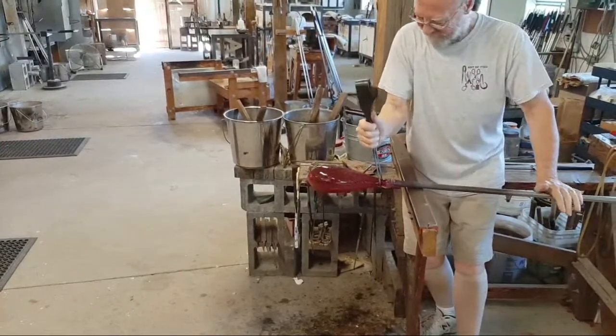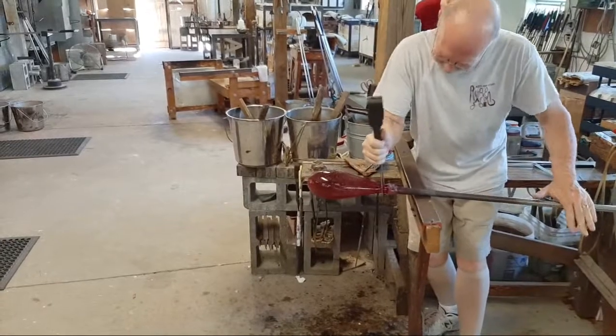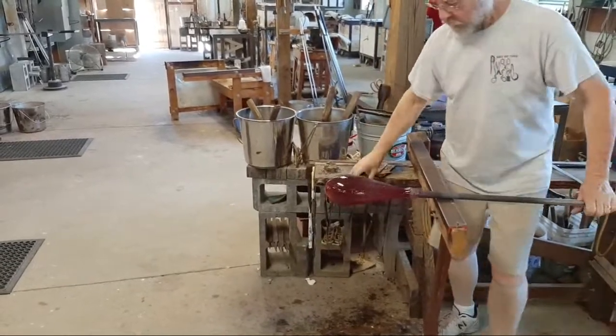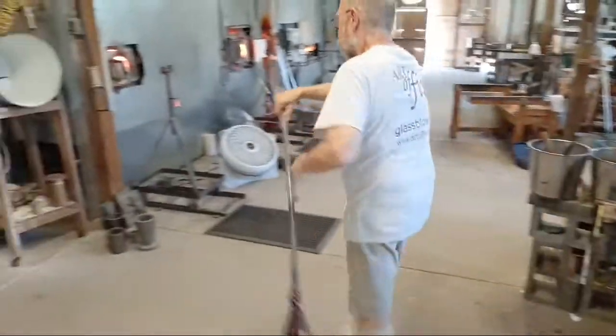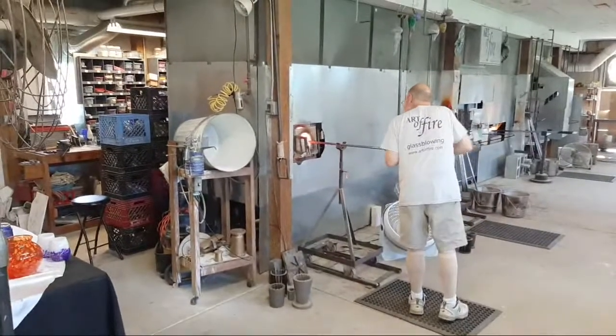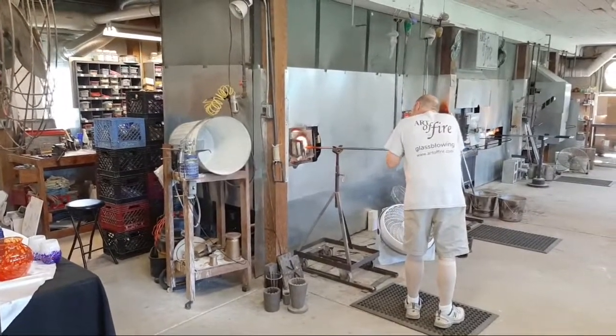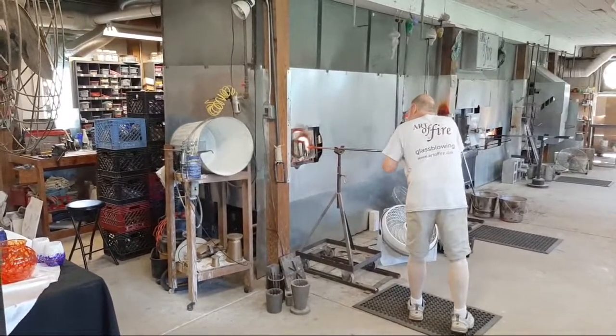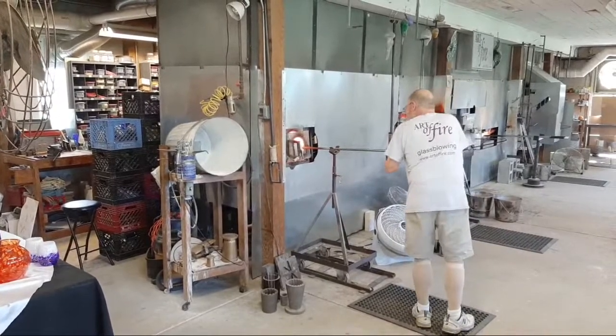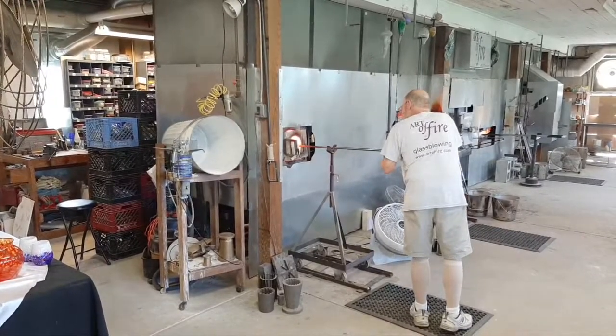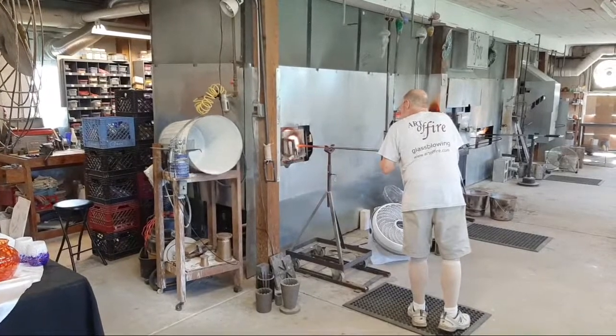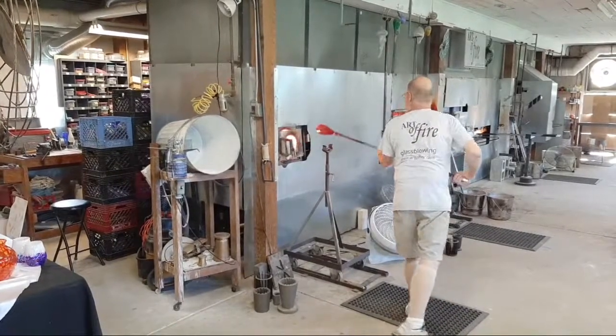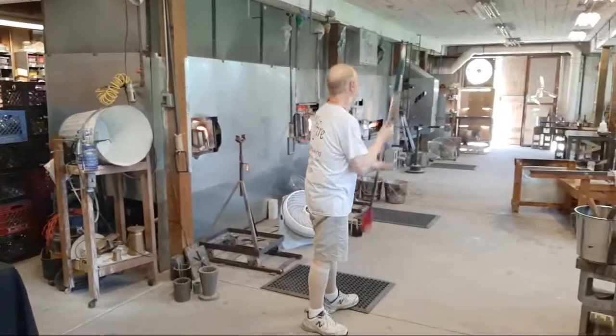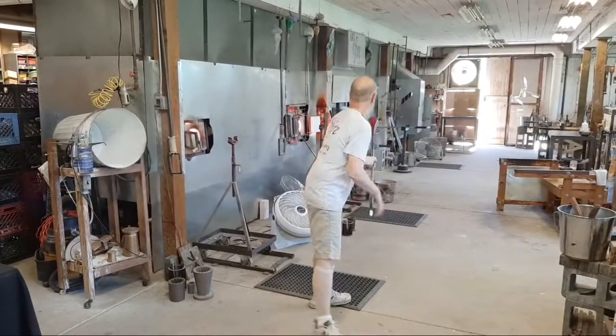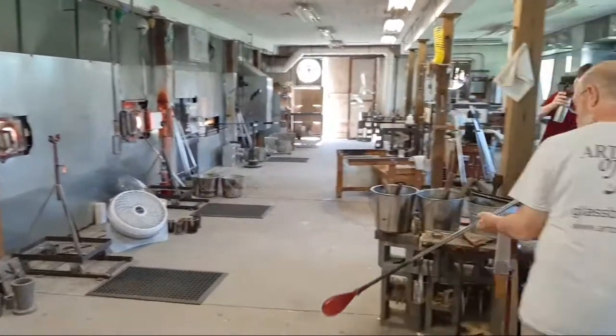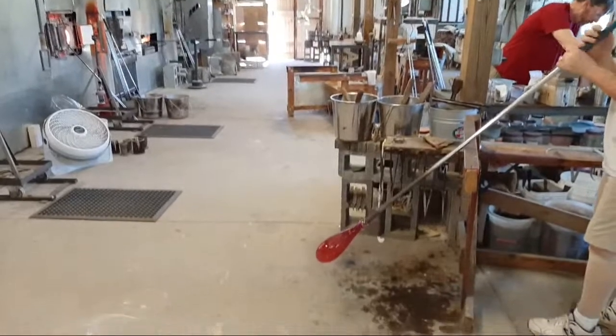When it breaks free of the blowpipe, the glass is going to come loose at its weakest point. And we want to make sure that the weakest point is right there at that neckline or jack line. Because if it's equally weak at the jack line and at the attachment to the other iron, we get a floor model. And we don't like those. So he's working this a little more. He wants a little more length. He had checked it with the calipers. He'll come back and probably check that once more. A little bit of air.